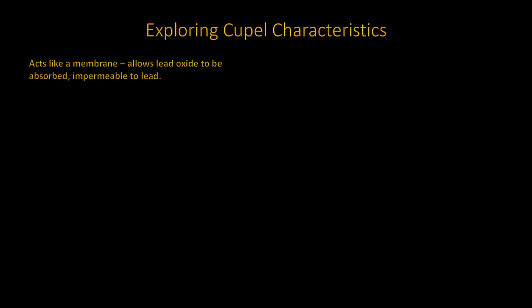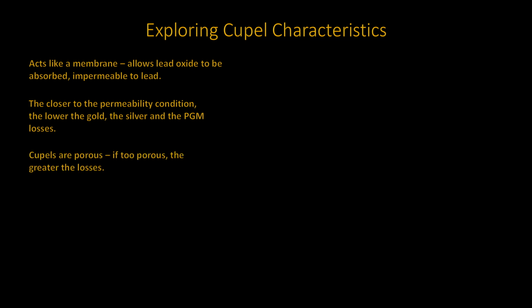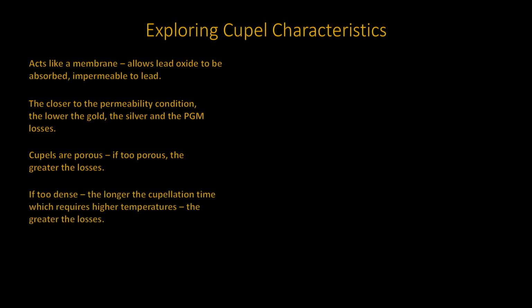Cupels can be thought of as a membrane that will permit absorption of lead oxide but will not be permeable to elemental lead. The closer that this characteristic becomes, the lesser the losses of any precious and noble metals due to absorption. If the cupel is too porous, an error in manufacturing, the greater the absorption factor will be, resulting in greater losses. On the flip side, if the cupel is too dense, a higher temperature and a longer cupellation time will be needed. This also creates losses due to volatilization.